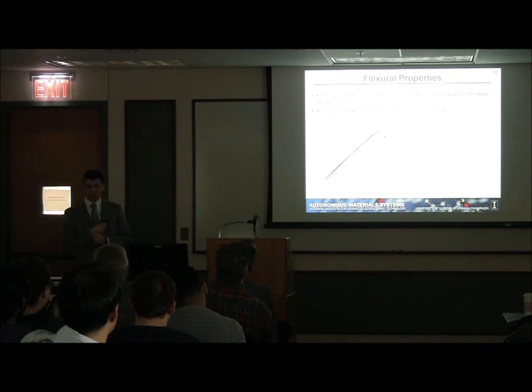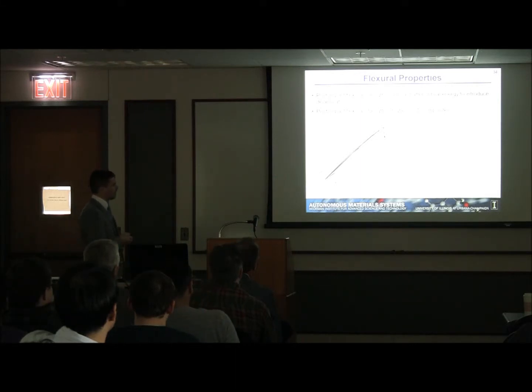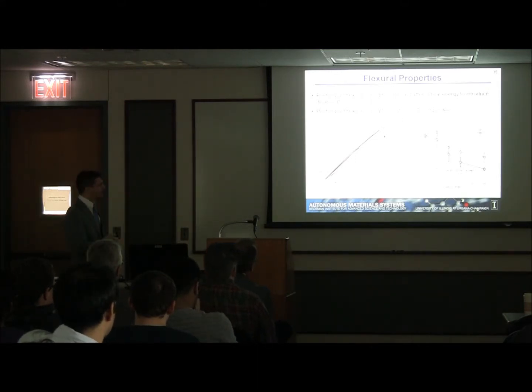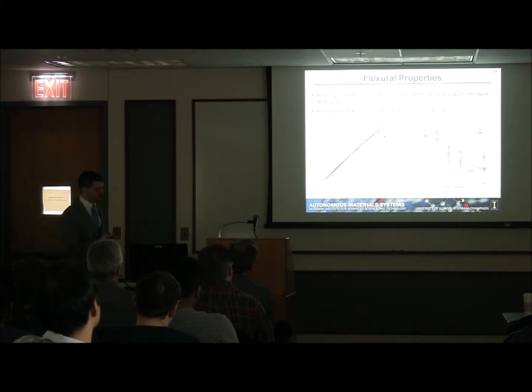Then we can take these damaged specimens and evaluate them in flexion. So if we look at typical stress strain curves for these samples, and we look at a variety of different impact energies imparted to those samples, we can see that as the impact energy increases, we start to see less and less stress at failure, and also lower moduli during the flexion testing. If we plot the flexural strength as a function of impact energy across those different impact energies, we see that with the 0 and 5 joule cases, the residual strength of these composites is roughly the same.